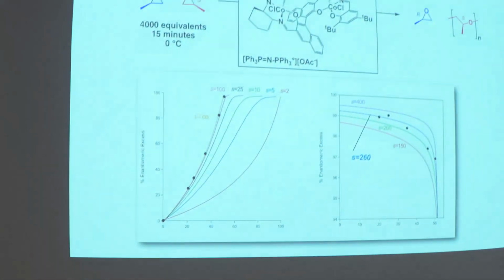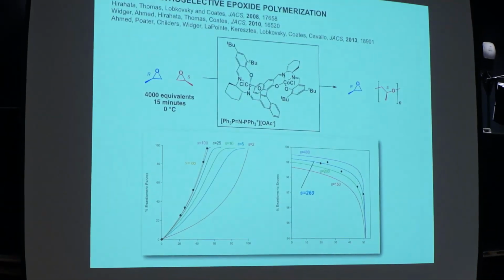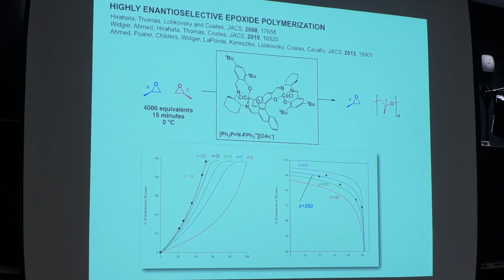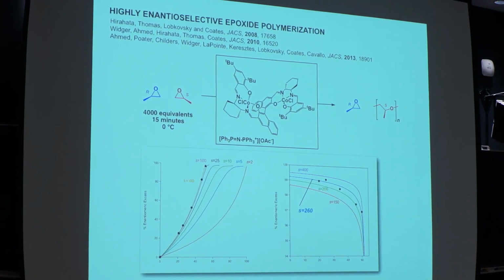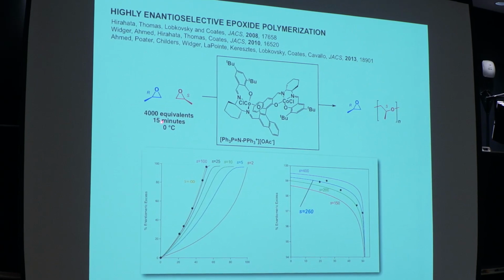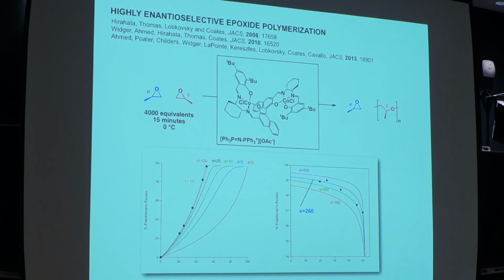So we add 4,000 equivalents of propylene oxide. We add in one equivalent of our catalyst. It turns out if you're not careful, these exotherm, because they make polymers so quickly, and epoxide ring opening is quite exothermic. So in about 15 minutes, this reaction was finished, even at low temperature. We looked at the product, and it went to about 50% yield, and the polymer made was very crystalline, which bodes well for a highly isotactic polymer and a very highly selective catalyst.